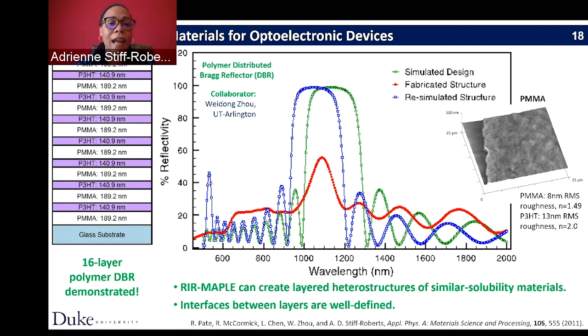And so the point here is not that we made a good DBR, because the reflectance is only 60% when we were shooting for 100%, but it does have the behavior of a DBR, which means that with the MAPLE process, we were able to control the film thickness and the interface quality well enough that the DBR function could be observed. And that's something that's extremely difficult to achieve in a solution-based process.